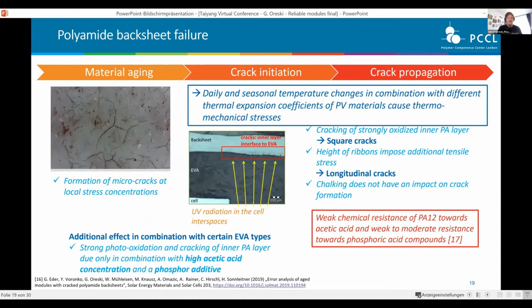But in general, the crack initiation and crack propagation happened because of the daily and seasonal temperature changes in combination with the different thermal expansion coefficients of the PV materials. So keep in mind, polymers have a 10 times higher expansion coefficient than, for example, glass. And this hindered expansion causes thermomechanical stresses. And that is the driving factor for the crack propagation.